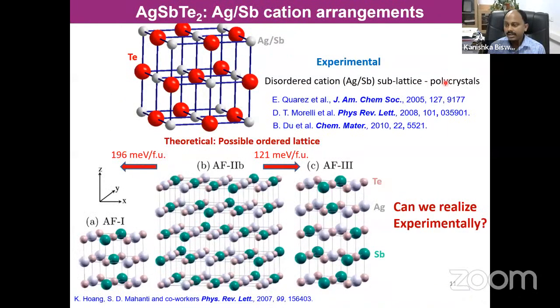This was discovered in the 1980s. And there are several groups working on this compound, and there are several experimental reports which claim that the silver and antimony are disordered in this position. And we have also synthesized it in our lab, and we showed by crystallography that silver and antimony are disordered in this compound. Then Mahanti's group at Michigan State published a paper in PRL in 2007.